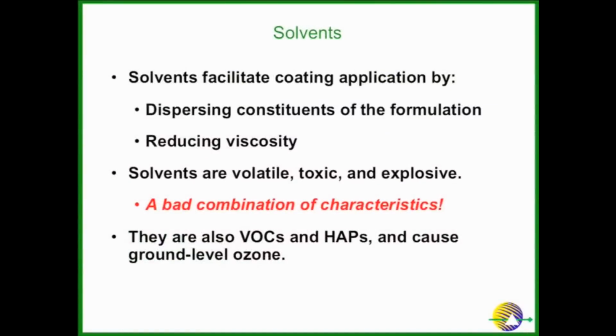Solvents are used because they disperse the constituents very nicely. I've talked about dispersing oil in water. This is much the same thing. They also reduce the viscosity. That's important because you're going to apply this with a brush. So it has to have a good low viscosity, but again, not too low. Of course, the solvents themselves are volatile, toxic, and explosive, which isn't a great combination of characteristics.